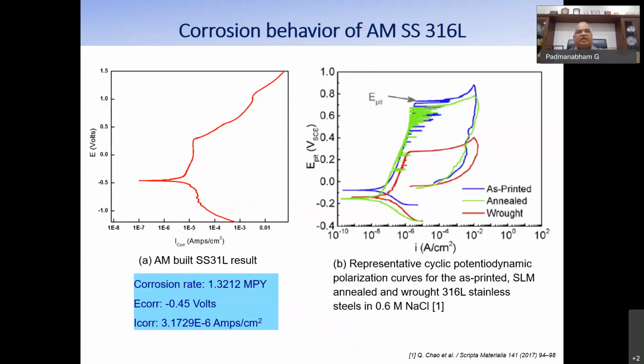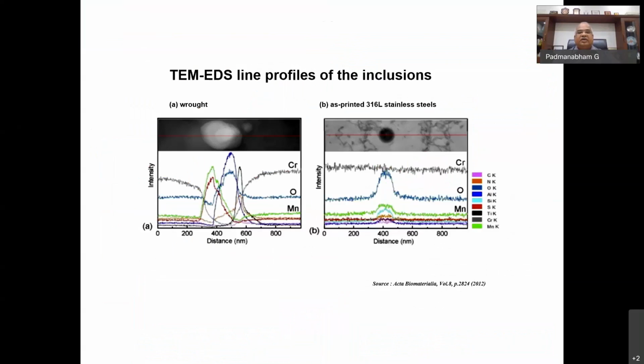But stainless steels are mainly meant for high corrosion resistance, especially pitting corrosion resistance. That also you can see from the potentiodynamic polarization curves, that the AM built SS316L is superior to the wrought 316L. You can see the corrosion rate, right? Even the corrosion voltage shows that it is superior. And why is it happening? If you take element mapping across an inclusion, you can see the manganese sulfide formation is suppressed, because of which chromium depletion is also suppressed, resulting in better pitting corrosion resistance in this material.